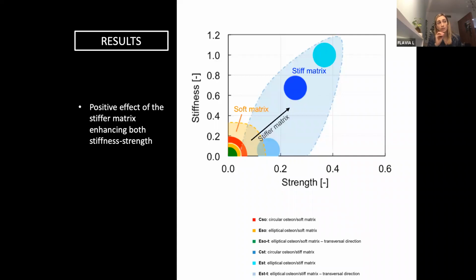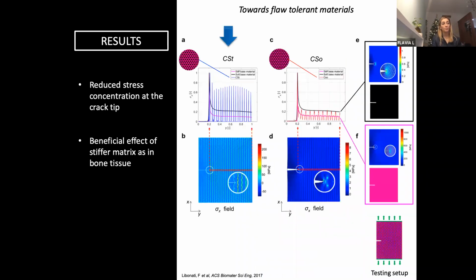Here, what we notice is the positive effect of a stiffer matrix, which really boosts the stiffness and strength combination with respect to a softer matrix. And the reason why can be provided by looking at the stress distribution. If we analyze the stress distribution, and this is again another powerful thing of using simulation, what we notice is that, of course, the difference with homogeneous materials is that we have a heterogeneous stress field, which provides dissipation of the energy and different mechanisms of energy dissipation, which all contribute to toughness enhancement.